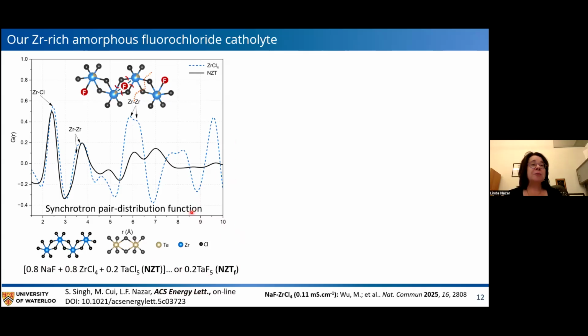So this shows the synchrotron pair distribution function of the parent zirconium chloride, which is shown here in the dotted blue lines, and that of what we call NZT, which is the sodium zirconium tantalum chloride. And you can see that we lose long-range order at about 8 angstroms almost completely by comparison to the parent.